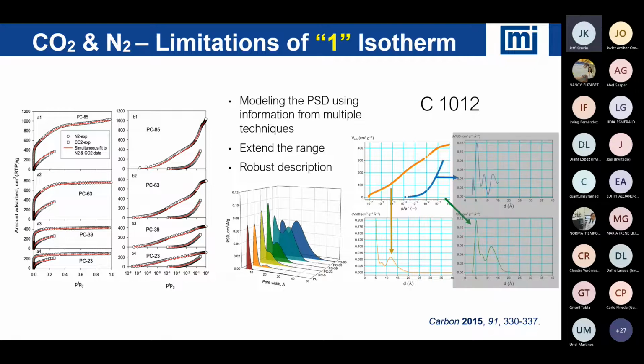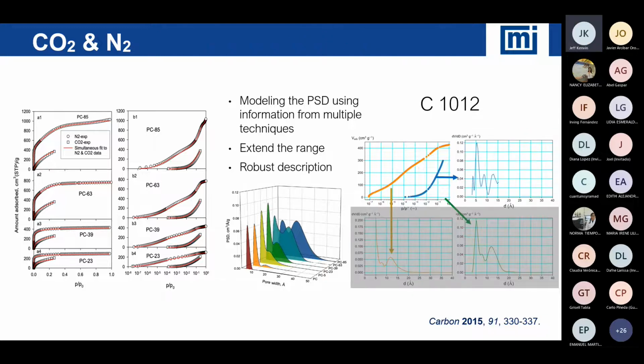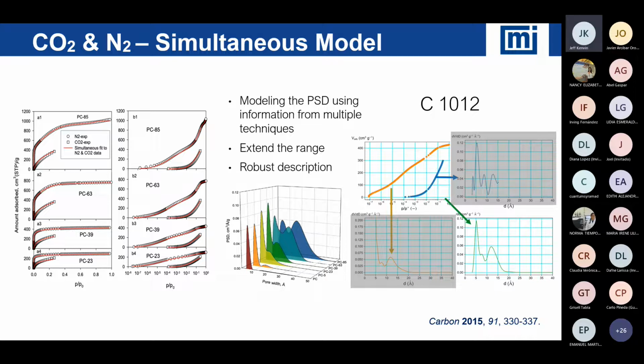And if we look at the adsorption related to it, the nitrogen you see, and that's the orange line, notice the nitrogen is limited to what can be learned about the material. So below 5 angstroms, a 0.5 nanometer, we really lose resolution with nitrogen. Similarly, if we use CO2, and that's in blue, we don't have much resolution above 10 to 15 angstroms. So we don't get a full range. If we take both isotherms together and model both of them at the same time, not model nitrogen, then CO2 and paste them together, but actually do a simultaneous modeling, we get a beautiful full pore size distribution. You see that in green.